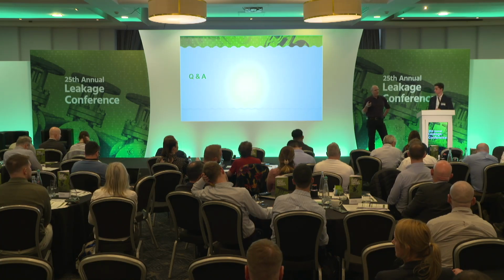With polyethylene, it's going to be the cross-linking inside the polyethylene that has to break. I'm looking down at Joe because you're the material scientist on this bit. The threshold for that is going to be a lot higher, I would have suggested, than 1 bar. Where we'd have to look is the joints.